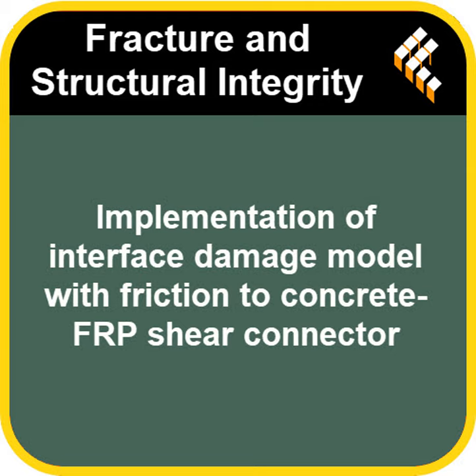Wow. So did this complex simulation work actually lead to practical design advice? Any recommendations for engineers building bridges? Absolutely. The study had clear takeaways for design. They found that a smaller radius of curvature results in a stiffer connector, even after some debonding has occurred. Combine that smaller R with higher friction, and you get a really positive effect on the overall structural stiffness.